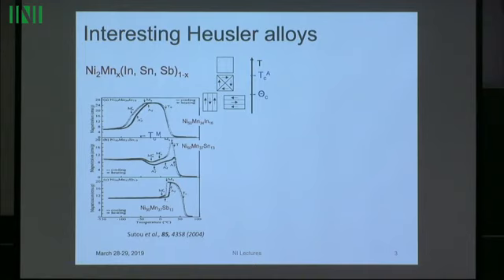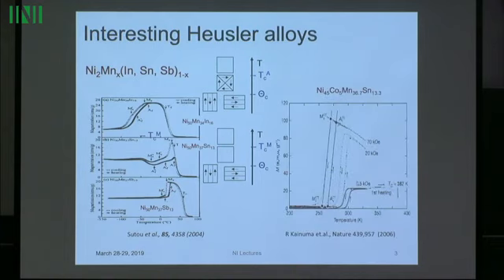In this case, the martensitic phase transformation is almost on top of the Curie point. So you could even say, effectively, the austenite is non-ferromagnetic. It transforms to ferromagnetic martensite. This is a particularly interesting case that caught our attention. Also, it's very interesting from a materials science viewpoint because it has this diagram.